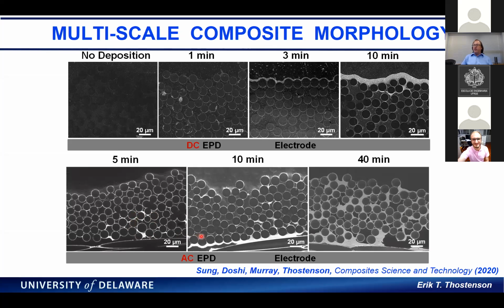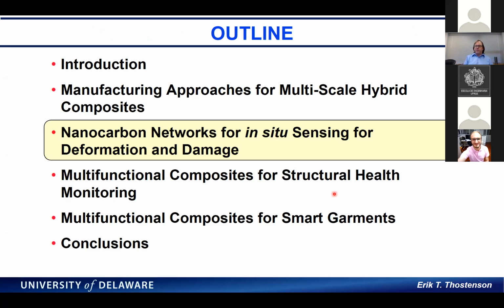And then over longer and longer time, we start filling in those gaps. And a lot of that depends on our processing conditions. So here, this is 10 minutes and 40 minutes, but we can control that also. So I think it's really not just raining down onto the fibers themselves, but actually this film grows over the fibers and around each fiber and is remarkably uniform. So that's really this enabling technology.